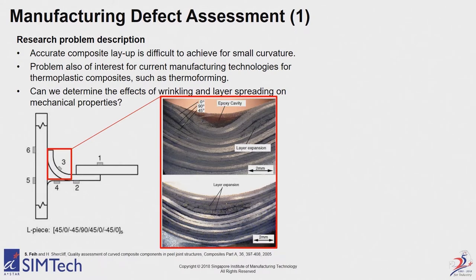So it's actually about manufacturing defects. I was working in joining, and the one thing that we saw when we actually manufactured these fairly thick and small radius pieces was that the carbon fiber layers did not align so nicely with the tight radius, especially on the inner radius side. We actually saw wrinkling, and we also saw layer expansion. So the question was, can we actually determine the effects of wrinkling and layer spreading on mechanical properties?